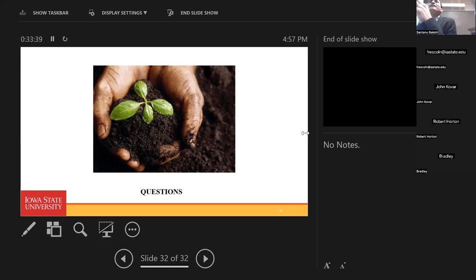Also, which time you are collecting the manure. Is it fall? Is it summer? Is it spring? So it varies widely. Based on these facts, we are considering the amount of nitrogen and phosphorus coming from the manure. It is not like direct manure application to the biochar; we are testing the manure at first. Okay, so it has X amount of P and Y amount of nitrogen, so we can customize how much manure we need to add to the biochar. Mixing biochar and manure, yes, it's a direct one. If you are diluting the manure, it would be diluted first and then mixed with the biochar. But in the chamber treatment, the diagram I showed previously of the bioreactor we are developing, that's a direct application of the manure into the chamber of biochar. So it goes in that way.